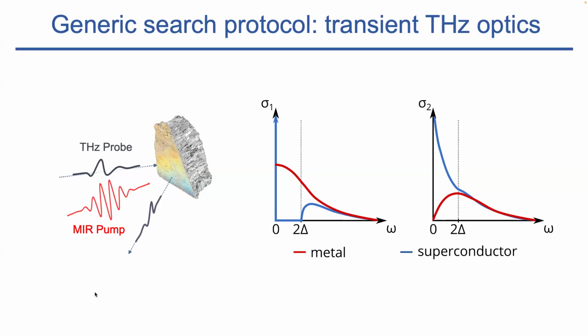Now, when you cool the material below TC, what you find is that in the real part of the conductivity, there's a gap opening and a pole at zero frequency. And the presence of this pole at zero frequency is manifesting a divergent imaginary part of the conductivity. Long story short, you want to pump a material, start from the red and go to the blue. And if you go to the blue, then I'm going to argue that gives you a necessary but not sufficient condition to state that you have discovered a light-induced superconducting state.